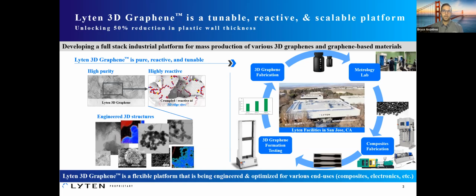Again, we nano assemble those from a pure hydrocarbon source. So what we do with the material and how we use that is, if you see here on the right-hand side, you have the 3D graphene fabrication. We then have a full metrology lab where we look at those materials and analyze those. So, some of your standard things like pore size distribution, Raman spectrum, et cetera. We also have our own TEM and SEM to look at these materials.